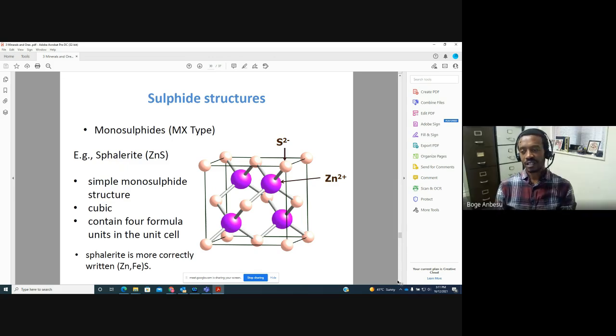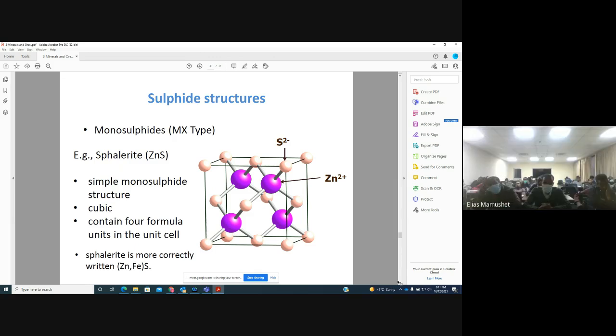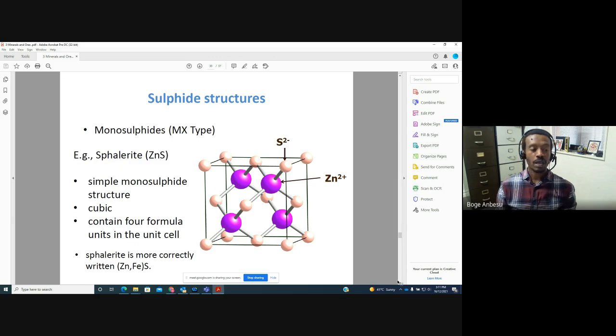So it is very difficult to find a zinc sulfide in pure form. Although I write zinc sulfide for sphalerite, actually in nature what you find is zinc iron sulfide. So when you take a sample of a zinc deposit and do assaying, you have lots of zinc, lots of sulfur, but sometimes you have lots of iron with it. And you might wonder, where is the iron coming from? My XRD is saying it is a sphalerite, and sphalerite is zinc sulfide, but the iron can actually be incorporated in the crystal system by replacing the zinc.